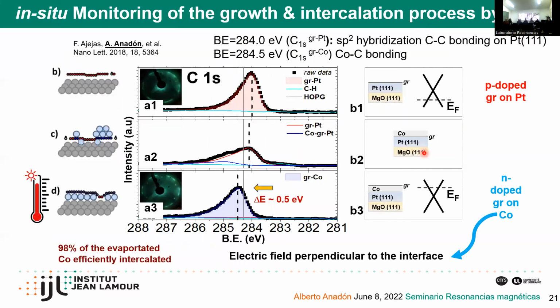And what we found by looking at the C1s peak of carbon in X-ray photoemission spectroscopy was that when we have a platinum graphene sample, our C1s peak was shifted to the right. So we have p-doped graphene when it's grown on platinum, only on platinum. But okay, now we put the cobalt by MBE on top of it, as I described in the previous slide. And there is a new peak showing up here.